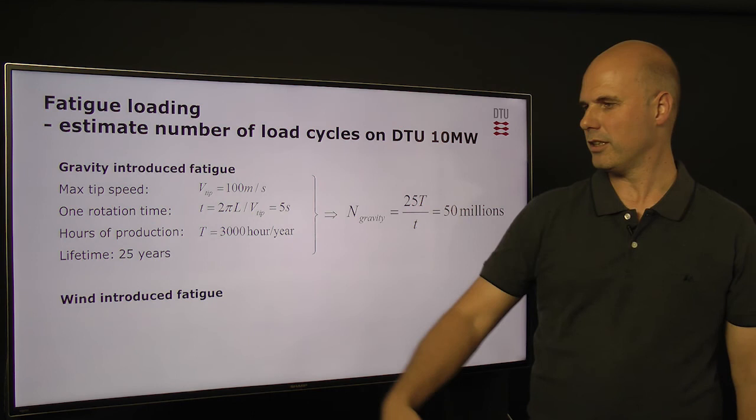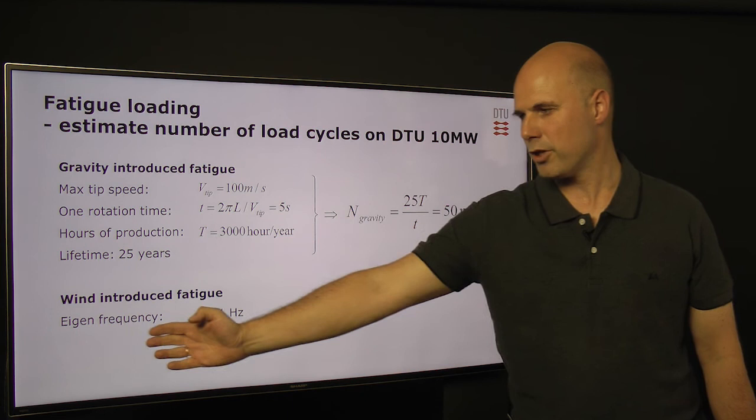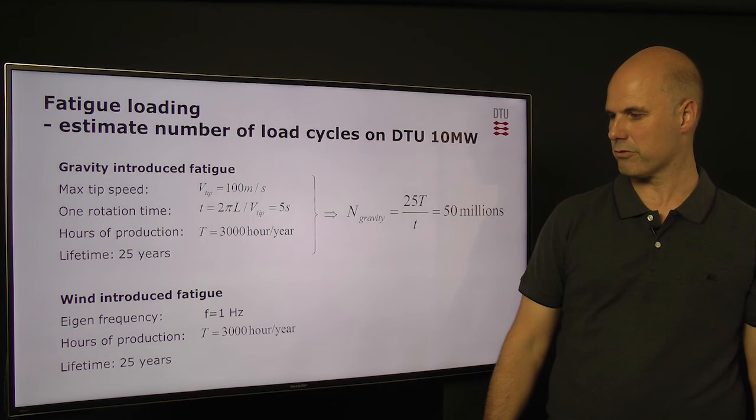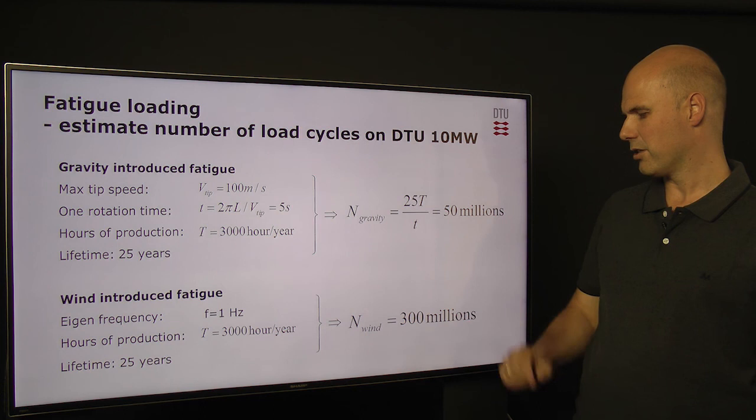Following the gravity load, we also have wind-induced fatigue. When estimating the number of load cycles from wind, the starting point is the eigenfrequency of the blade, which is on the order of 1 Hz for this turbine. Again taking 3,000 hours of production per year and a lifetime of 25 years, we reach a number of load cycles from the wind load of 300 million.